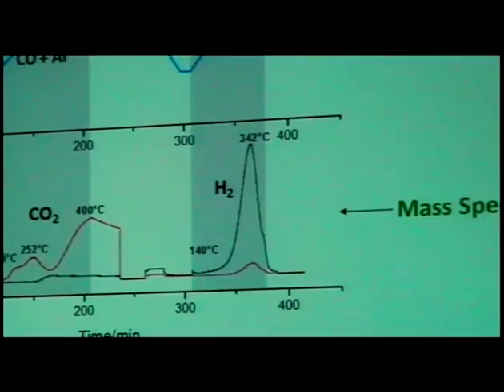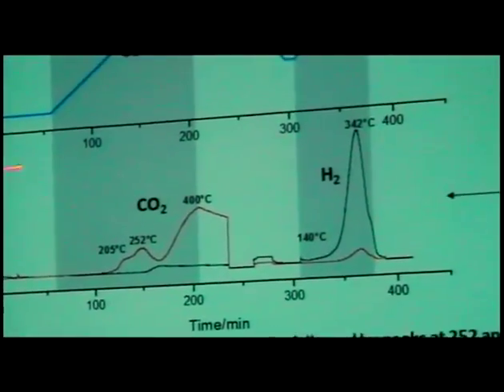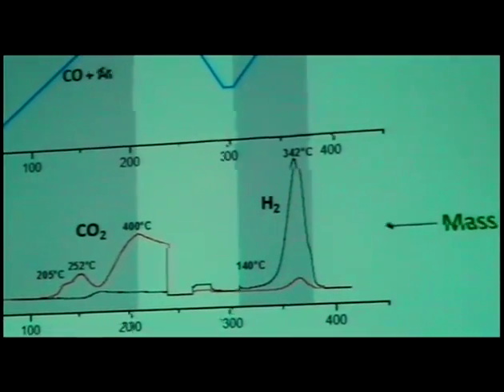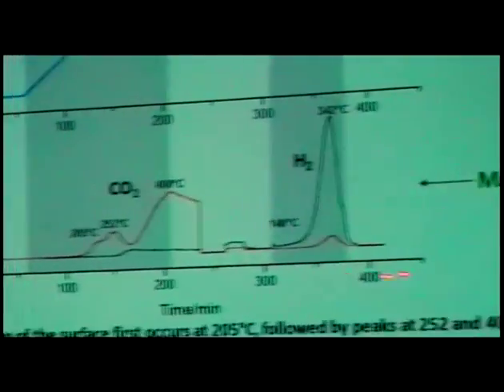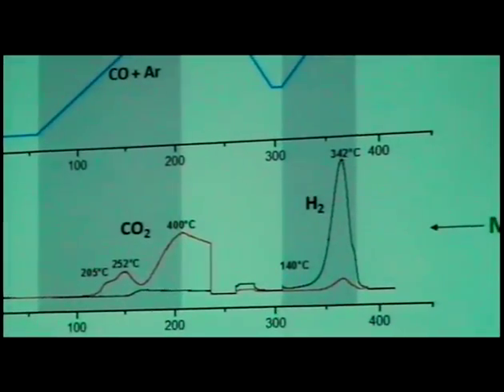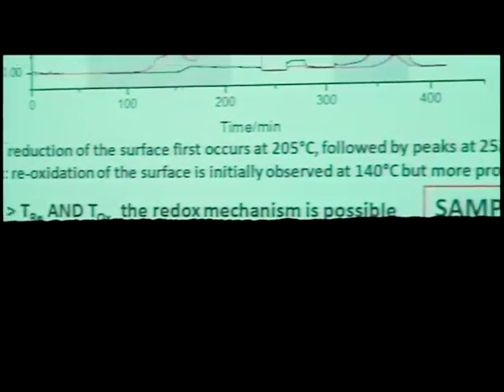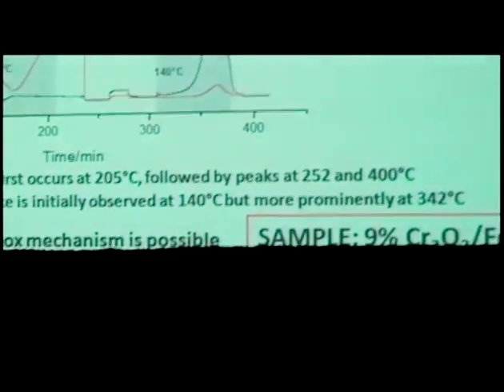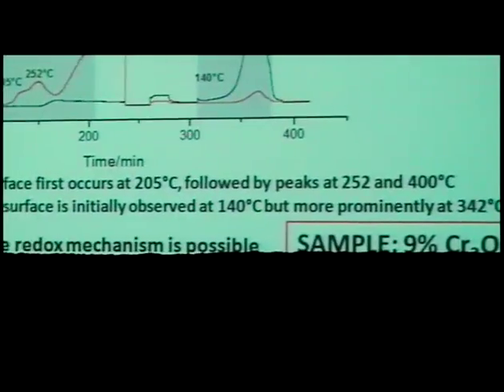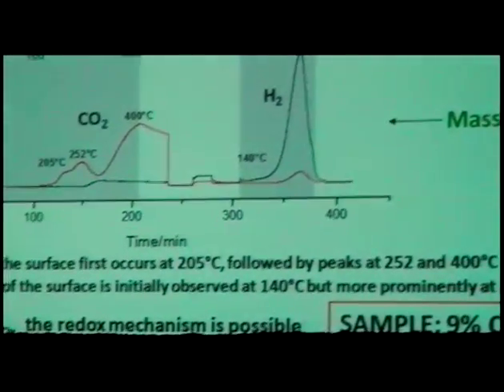Again, the shaded area is where we would have seen formates that have been there. So the redox behavior is consistent with the mechanism being the redox mechanism, because you can do redox at a very mild temperature, much lower even than the typical water gas shift reaction for this catalyst.